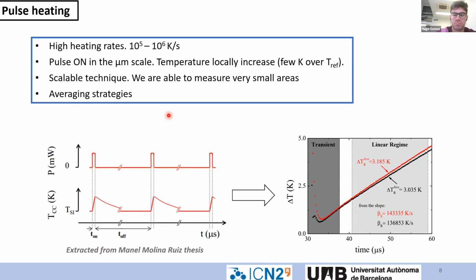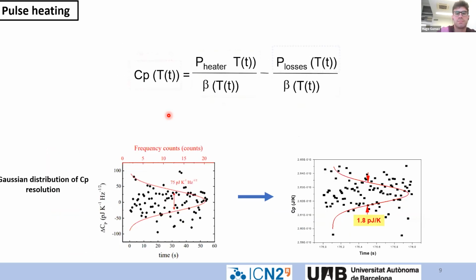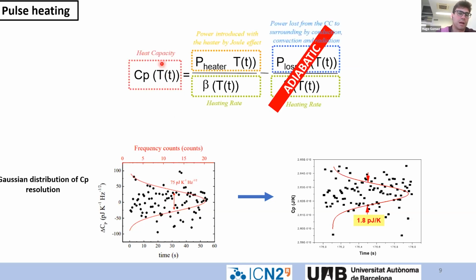We can have a 15 by 15 micron calorimetric cell, and we can access whatever material we are placing in that calorimetric cell. If we take a look at the equation for this material, we have the heat capacity, the power that we introduce, and the heating that we produce by Joule effect. The heating rate is also really important. We don't have any power losses, or at least nothing we need to take into account, because there is no conduction, convection or radiation in this case.